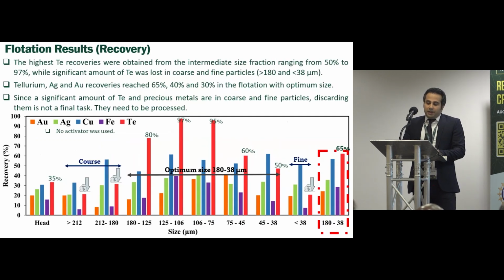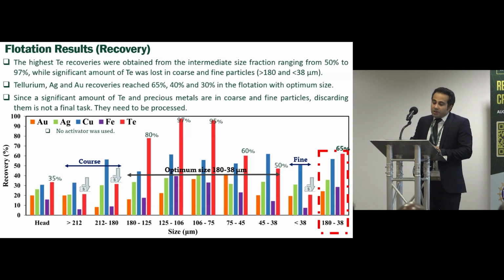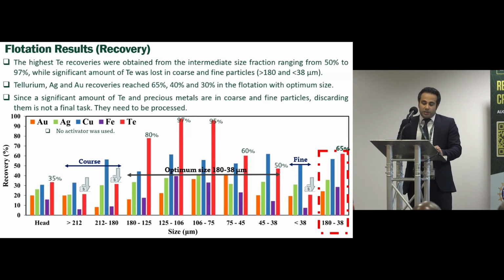The highest tellurium recoveries were obtained from the intermediate size, ranging from 180 to 38 micron, ranging from 50% to 97%, and a significant amount of tellurium was lost in coarse and fine particles. Tellurium, silver, and gold recoveries reached 65%, 40%, and 30% in the flotation with the optimum size. Since a significant amount of tellurium and precious metals are in coarse and fine particles, discarding these particles is not our final goal. We are exploring several methods to recover these particles.